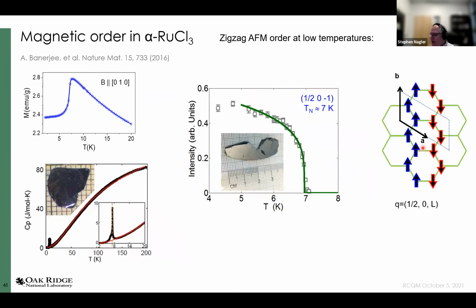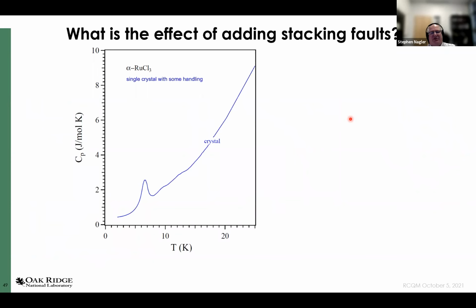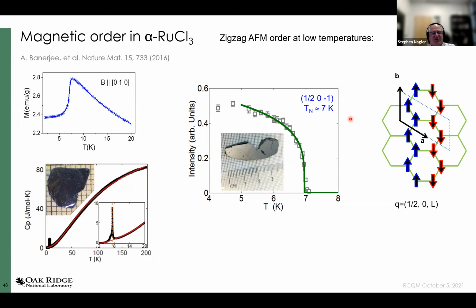In any case, once we had them, and again, I apologize for only showing Oak Ridge data on this, but we only have an hour. What you find is that this stuff orders antiferromagnetically in a zigzag phase at low temperatures. So here you see a couple of pictures of different samples. For what I'll call a pristine sample, you see a single transition around 7 Kelvin. Here you see it in the susceptibility. Here you see it in the specific heat. And here's a measurement of a neutron scattering peak. And indeed, this does correspond to the zigzag phase. And it corresponds to the zigzag phase with a 3-layer periodicity repeat in the magnetic structure. Now, you'll notice that this is a very sharp specific heat peak, relatively speaking.